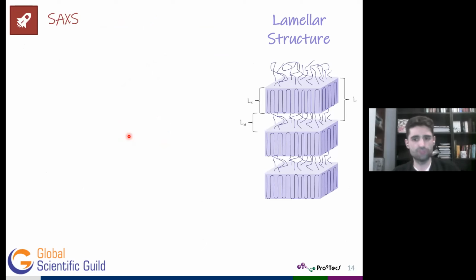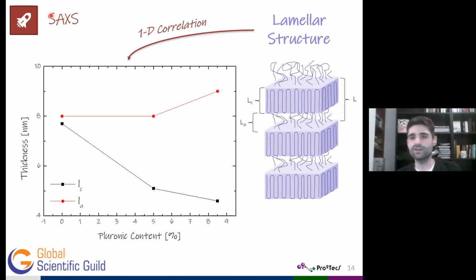On the other hand, the morphological parameters, including the long period and also the crystalline and amorphous layer thicknesses associated with the lamellar structure, which is obviously typical of PCL, could be extracted from such results. Indeed, we apply a 1D correlation according to some previous investigations to obtain those parameters. As we can see in that graph, although no significant influence can be found on the amorphous layer, the incorporation of pluronic into PCL dramatically reduces the thickness of the crystalline layer, as we can see in that reduction.